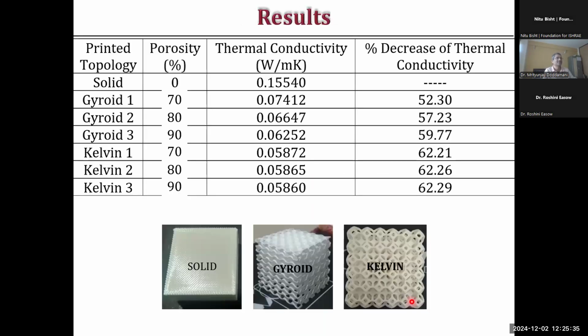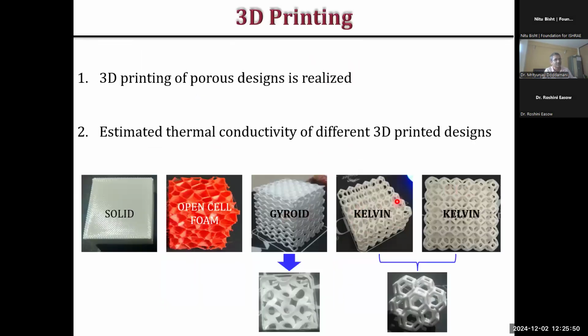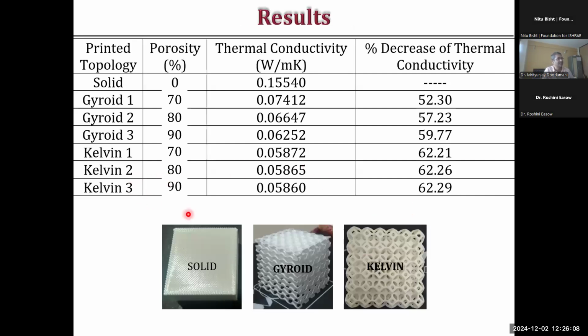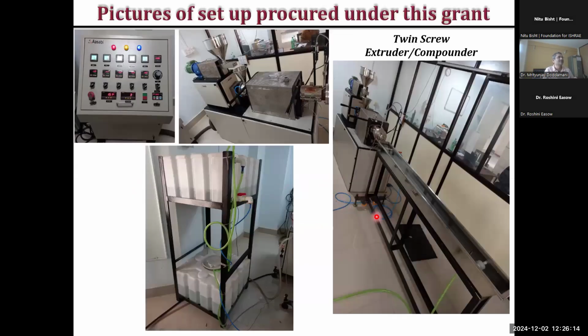Then we did experimental measurements on thermal conductivity as per the ASTM standard. With the Kelvin structure, these are non-foamed ones, please. So all these struts are solid ones. We could see at 90% porosity, so 90% printing is also possible. Now, why I am saying 3D printing here, I believe all of you might have easily understood, because in conventional manufacturing, producing such a Kelvin structure is, as of now, not possible. So this is where advanced manufacturing comes into the picture and helps us in achieving a high level of porosity. This system was funded by ISHRAE.